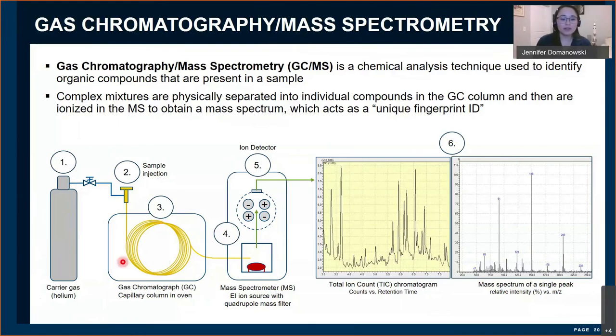So as they separate out into the individual components, they'll reach the detector or the mass spectrometer at different times. So when they reach the MS, they will ionize and then they'll be separated based on mass. So then what you end up with is a chromatogram where here each of the individual peaks are individual compounds. And then you have a mass spectrum that's paired with a peak. And this acts as a unique fingerprint ID of the compound. So that's how we use GCMS, and it's very helpful in our analysis.